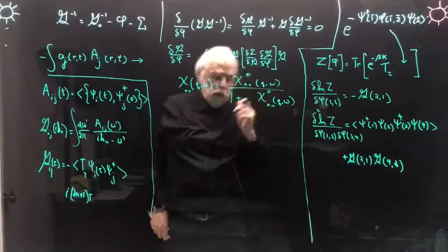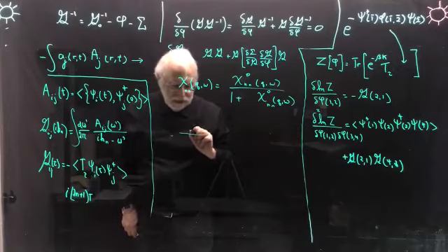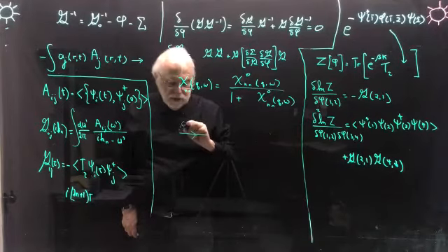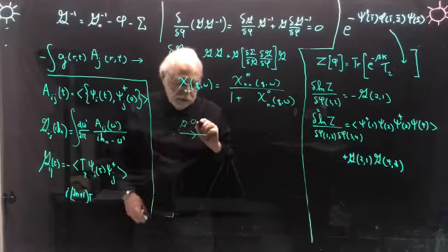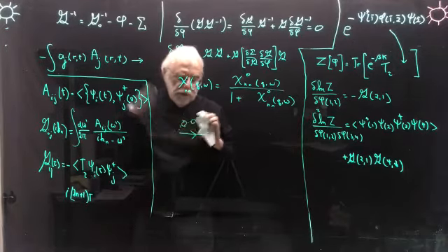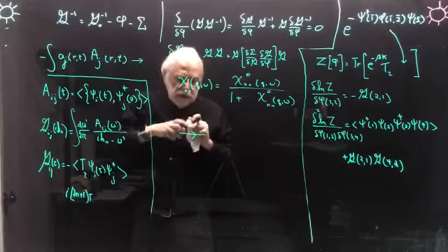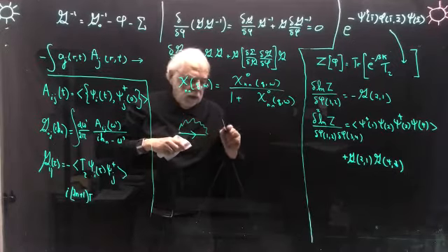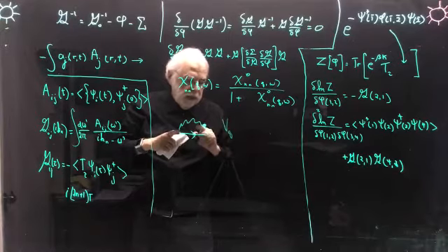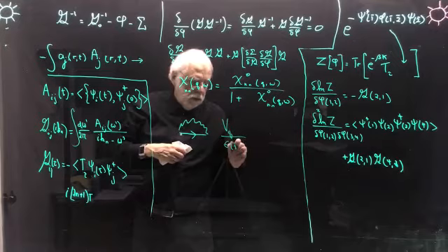Oh, I forgot to mention, very important. The other lesson for the electron gas is that we need to use the screened interaction. The Hartree-Fock result is completely crazy for the electron gas. So for the self energy, we need to put here not the bare Coulomb interaction but the screened Coulomb interaction, divided by epsilon of q and omega.